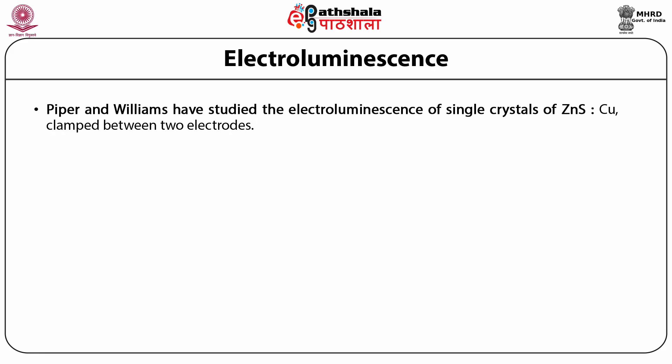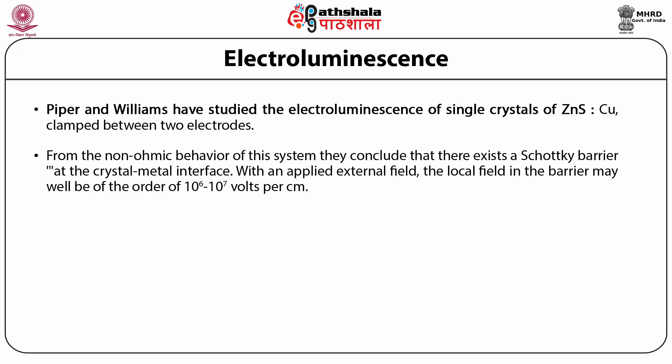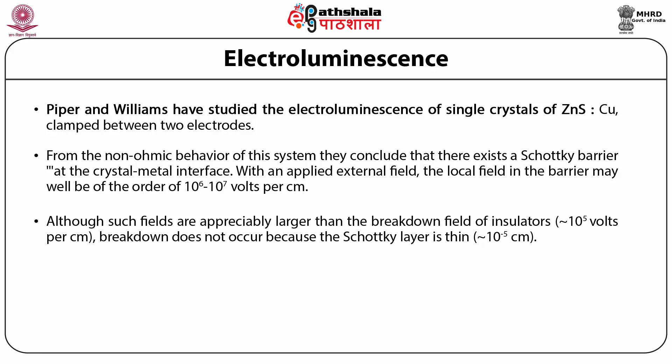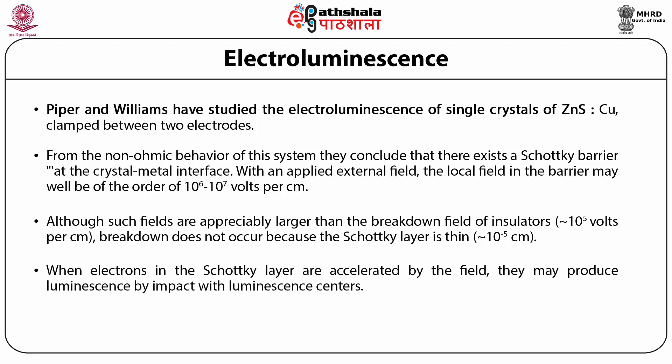A possible explanation of intrinsic electroluminescence involves the emptying of traps by the field, subsequent acceleration of electrons in the conduction band, and excitation of centers by these electrons. Piper and Williams studied the electroluminescence of single-crystal zinc sulfide with copper, clamped between two electrodes. From the non-ohmic behavior of this system, they concluded that there exists a Schottky barrier at the crystal-metal interface. With an applied external field, the local field in the barrier may be of the order of 10⁶ to 10⁷ V/cm. Although such fields exceed the breakdown field of insulators (~10⁵ V/cm), breakdown does not occur because the Schottky layer is thin (~10⁻⁵ cm). When electrons in the Schottky layer are accelerated by the field, they may produce luminescence by impact with luminescence centers.